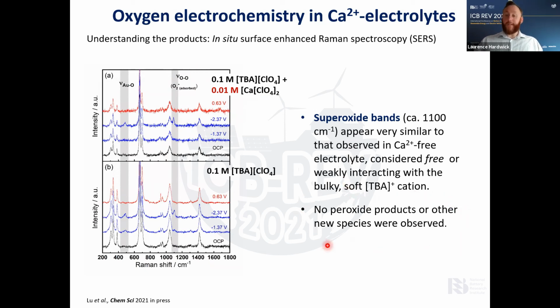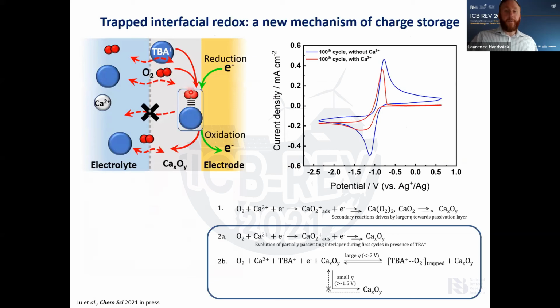And just to note, what we didn't observe was any other type of calcium species, be it calcium superoxide or calcium peroxide. We didn't observe any bands of these compounds forming. Whatever the nature of this layer is, it is some sort of amorphous calcium oxide layer on the surface that has the ability to trap, to not allow the diffusion out of this product of the TBA and the superoxide. And in the electrochemistry, you note that this oxidation peak does not have this very nice diffusion tail. It looks almost like we're stripping a metal from a surface. So we have a very abrupt and sharp peak for the oxidation. And this also guides us to think about this trapped species in this calcium oxygen interlayer in this system.